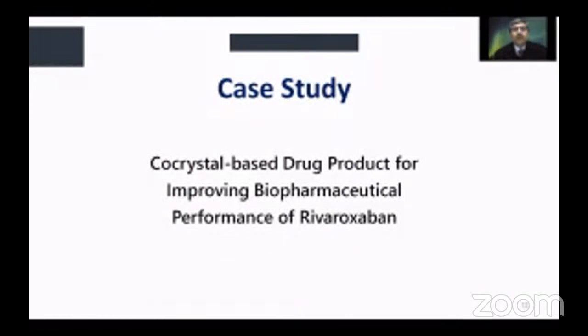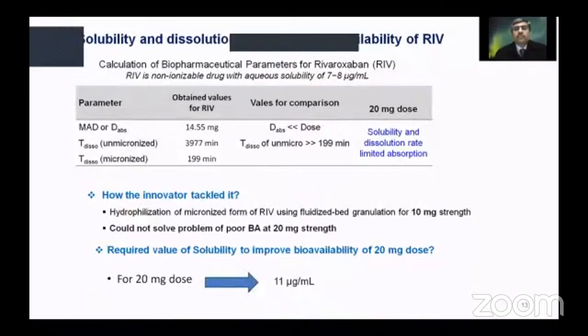We now move over to a case study wherein we will take up rivaroxaban as the drug candidate and talk about a co-crystal based drug product for improving the biopharmaceutical performance of rivaroxaban. Rivaroxaban is a drug candidate which has solubility and dissolution rate limited oral bioavailability. These are the calculations of the absorbable dose and the time of dissolution, which prove that for the 20 milligram dose, solubility and dissolution rate are the limiting factors for oral absorption.